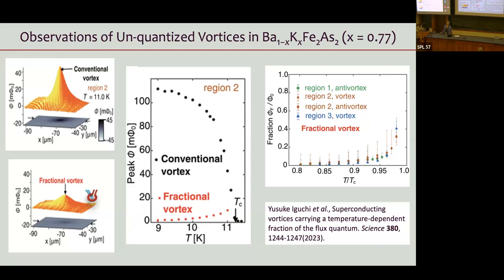And he found that this effect was strongest near the critical temperature, which is where you might naively think that the interband coupling might be weakest, although I don't know if there's a strong theoretical justification for that. And then he found that the fraction of flux that was carried in these fractional vortices, as I say, becomes larger close to the critical temperature.